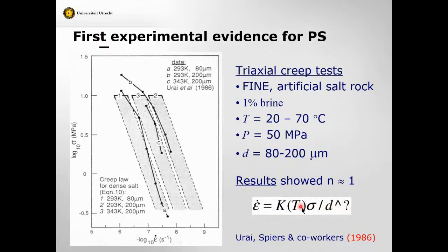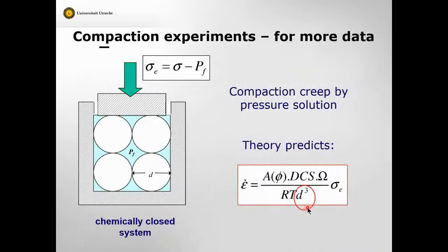we couldn't constrain very well the sensitivity. So what did we do? We started doing compaction experiments where we could control the grain size very well. And we developed a theory for the rate of pressure solution in a granular material. It's exactly the same, but it contains here a porosity-dependent term. So the strain rate depends on the applied stress linearly, on the grain size cubed down here. And there's a porosity-dependent term.